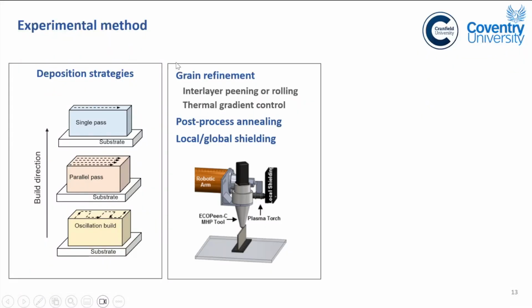Then for the grain refinement, this is to control the columnar beta grains in titanium, just to make them more equiaxed, so as to have better material properties and to reduce the anisotropy, the scatter and the design allowables. So they have tried interlayer hammer peening or rolling, layer by layer, but they also tried thermal gradient control. And the second one would be cheaper, not involving any mechanical deformation layer by layer.